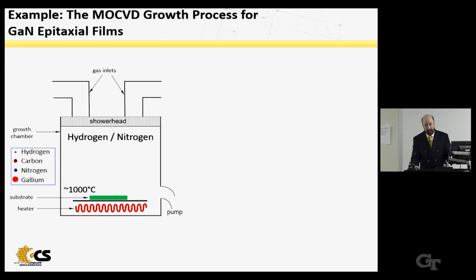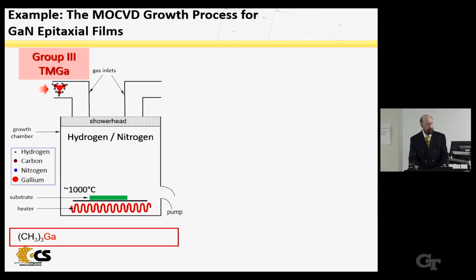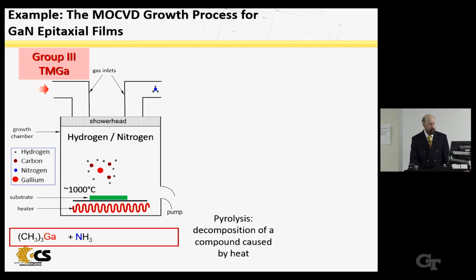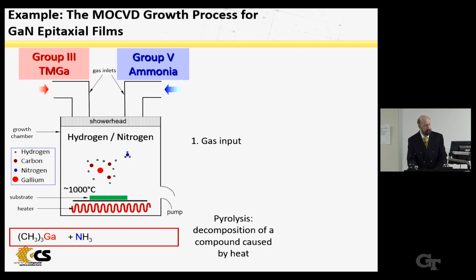We have a reactor chamber. In this case, it's often stainless steel in today's technology. And we have a substrate at around 1,000 degrees. We introduce trimethylgallium, a simple methyl compound with 3 methyl radicals on a gallium atom. That gets pyrolyzed. And then we also inject ammonia, NH3, a nice simple molecule with 3 hydrogen and nitrogen.